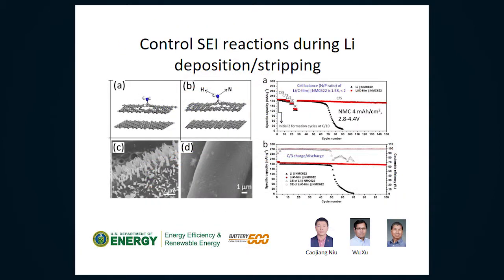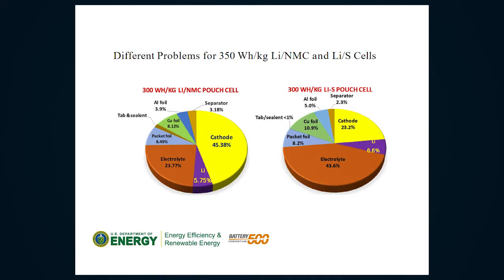It gets aggressively worse when you increase the cathode loading to that of a realistic cell of more than 300 watt hours. That's the minimum cathode material you need to have, at a different charge rate. Then you can still cycle, but the number of cycles you can achieve is significantly reduced. Now you really need to do this calculation: if you do the NMC system, how much cathode, anode, everything included, you need in this cell, and do it in the right voltage window. Or you do the same thing for lithium sulfur. We'll talk about that in a little bit. That's where things become very, very difficult.